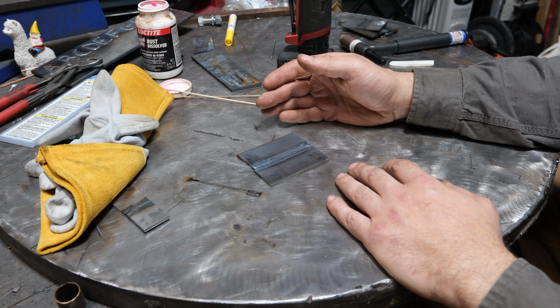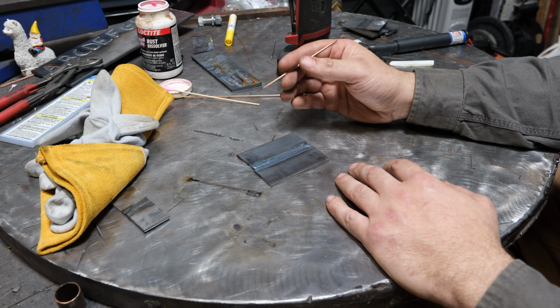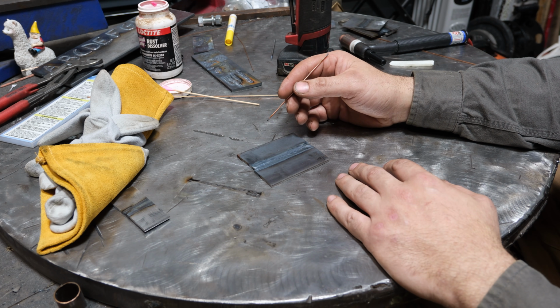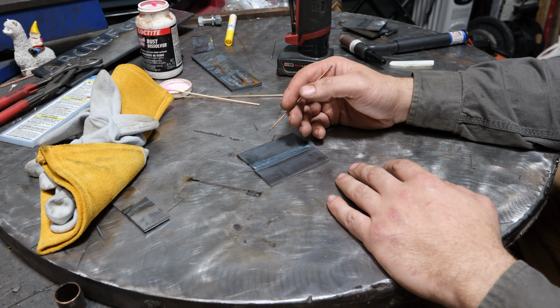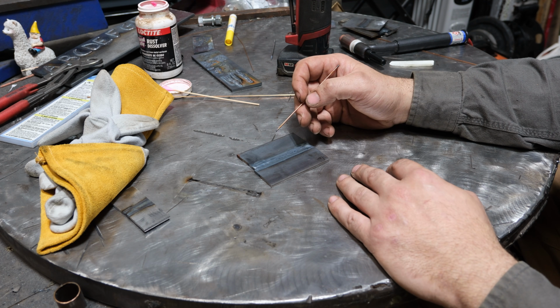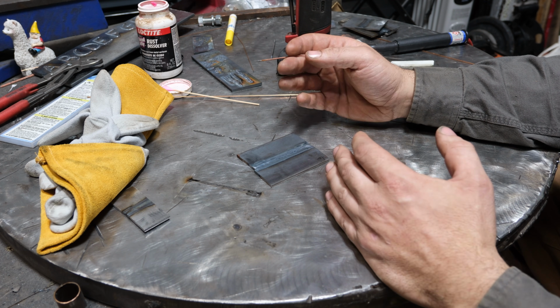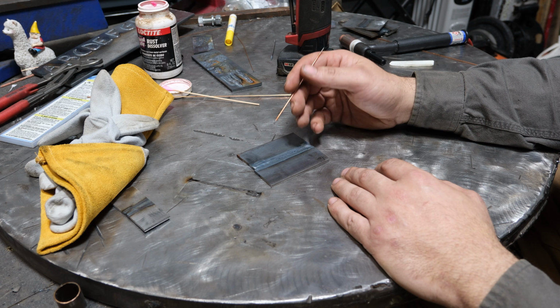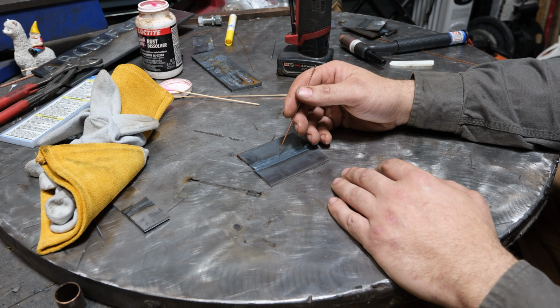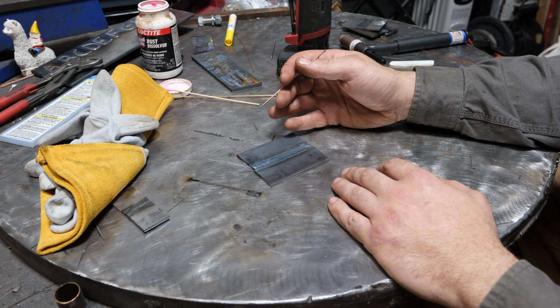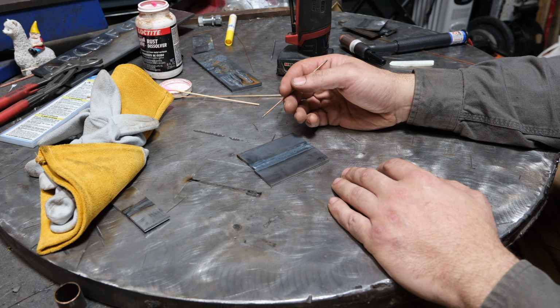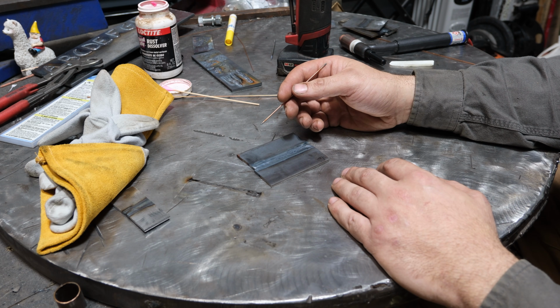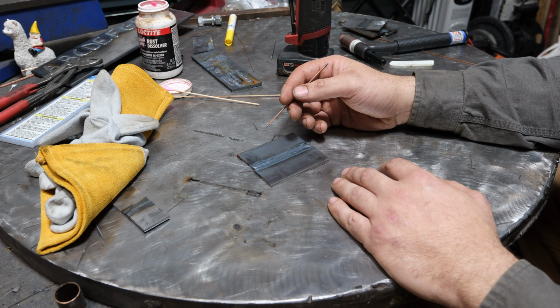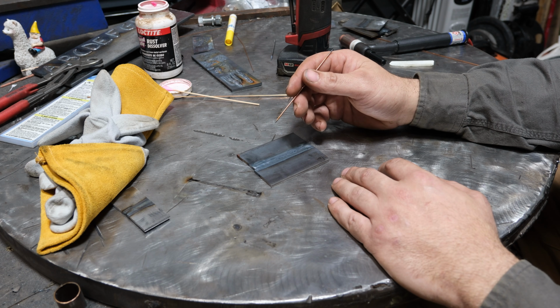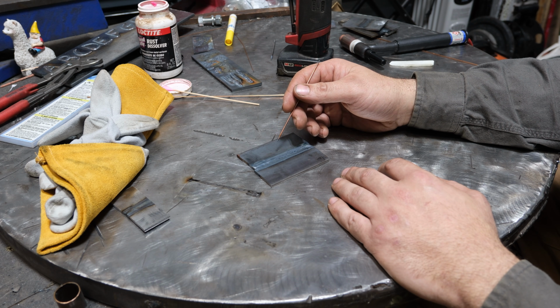And again, I can't stress to you guys how important it is to move at a moderate pace with the proper heat input, because you will not achieve any kind of fusion. And you saw it in the video how bad it can be if you run too fast. You basically don't fuse anything. So your travel speed is of the utmost importance. You must go slow. TIG is a very slow process in comparison to almost every other form of welding. Do not treat it like stick. Do not treat it like MIG, especially spray arc or dual shield. Those have nothing in common with the travel speed of TIG.